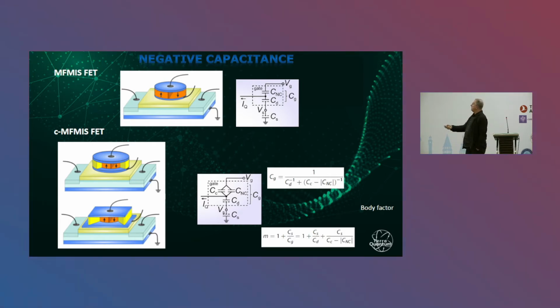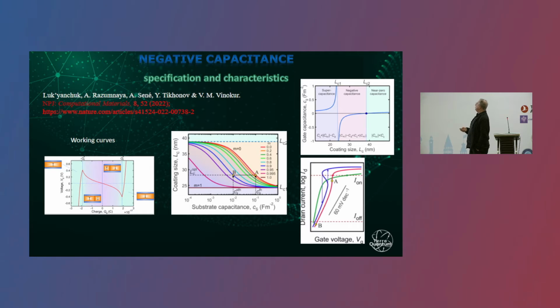But we can immediately make a slightly more complicated device. We can coat this ferroelectric with the usual dielectric one, and then the effective circuit is like that. It's a little bit boring analysis, but it's available to a first year student, that if we change the size of our dielectric coating, we can change the characteristics of our field effect transistor as much as we wish. We can achieve all these best possible characteristics. Let me find where it is. Okay, actually it's here.